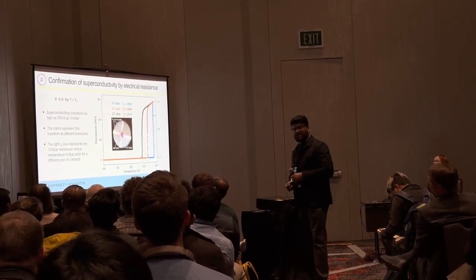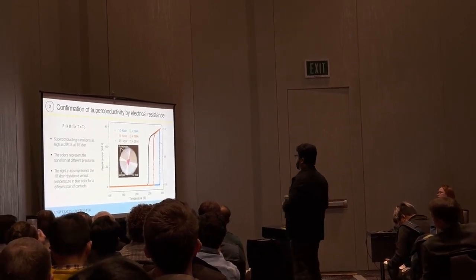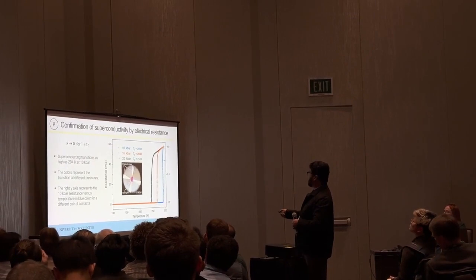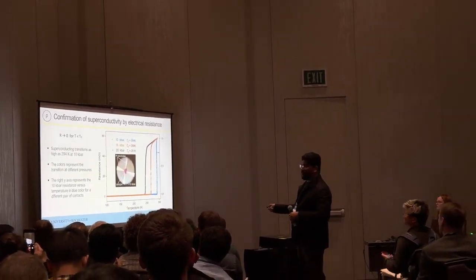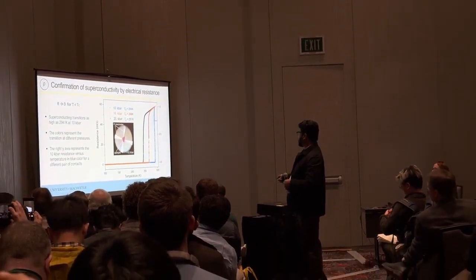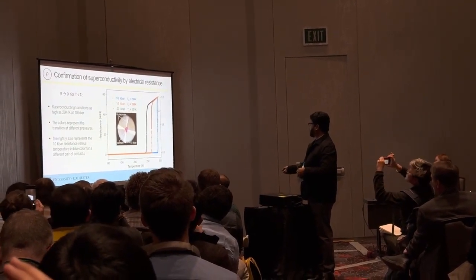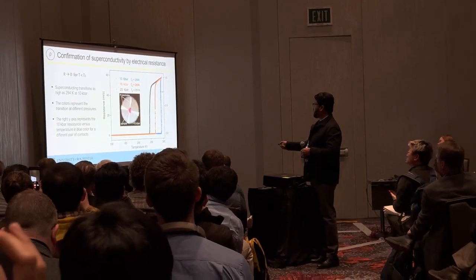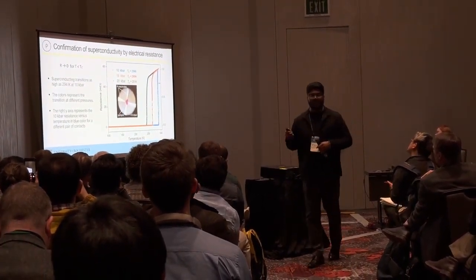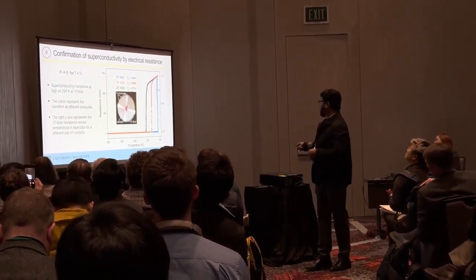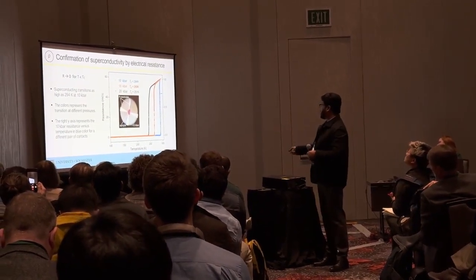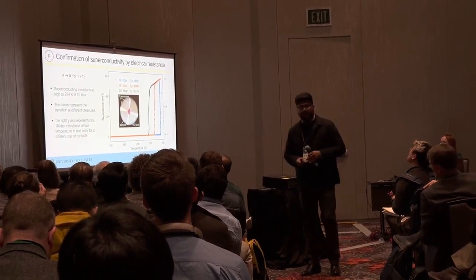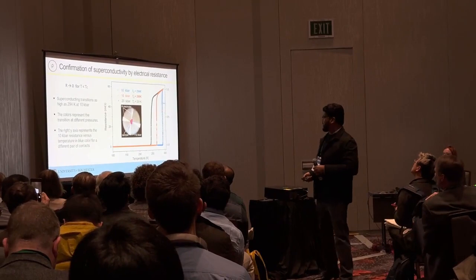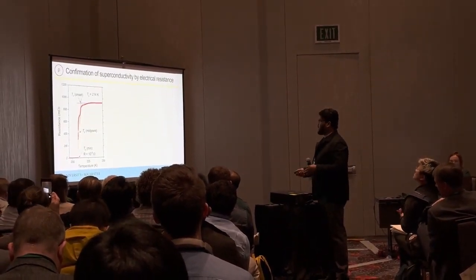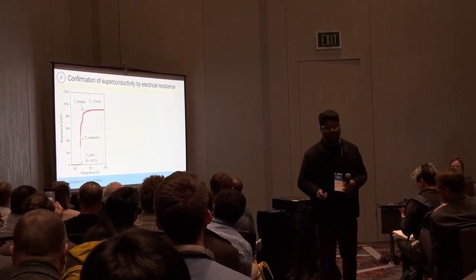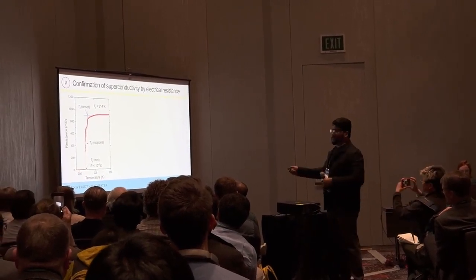So the first one, electrical resistance measurement. What you're seeing here is the conductivity measurement as a function of temperature. The first one, the blue color one, at 10 kilobar, Tc is as high as 294 Kelvin. The blue one right here, you see a drop in electrical resistance to 0. So the right side axis belongs to this blue color curve. And then you see two more pressure points, 16 kilobar and 20 kilobar, at 269 and 251 Kelvin. With applied pressure, there is a suppression of the Tc, and also you see the broadening of the transition. And the inset shows the picture of the sample with the electrical leads to measure the conductivity properties. Defining the Tc, different groups take onset or midpoint or the minimum value. All the values that we reported in our discovery are the onset of superconductivity.